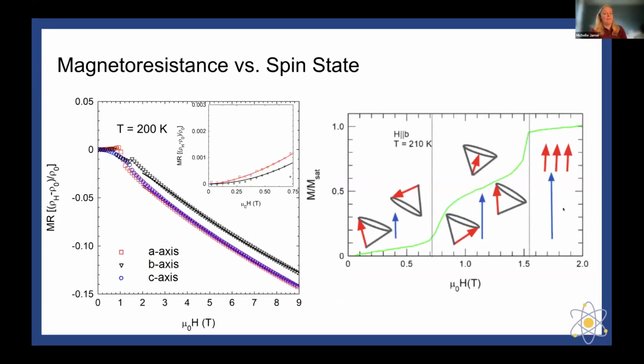And so what we can really start to think about here is the magnetoresistance versus spin state. So to the left, I have data at the 200 Kelvin temperature, and to the right, I have the magnetization data at 210 Kelvin.